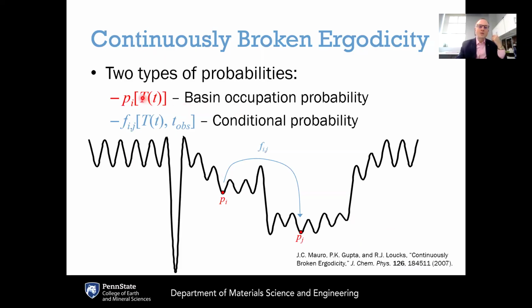Rather, we have one set of probabilities, which are the P_i. The P_i would be the probability of the system occupying a given microstate i. So that is this basin occupation probability, P_i. And then if you allowed the system to evolve for some observation time scale, over some observation time t observed, if you were to start in a particular microstate i, the second probability is the conditional probability F_ij, which is the conditional probability if you start in basin i that you would end up in some basin j after propagating the system for that amount of time.